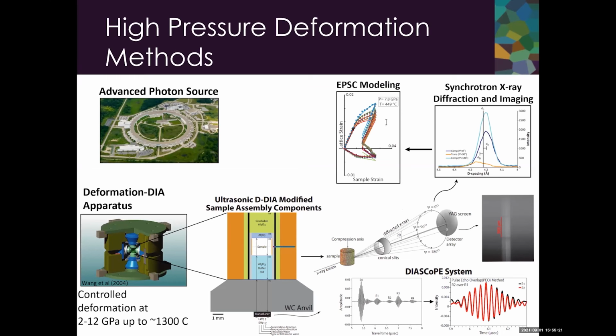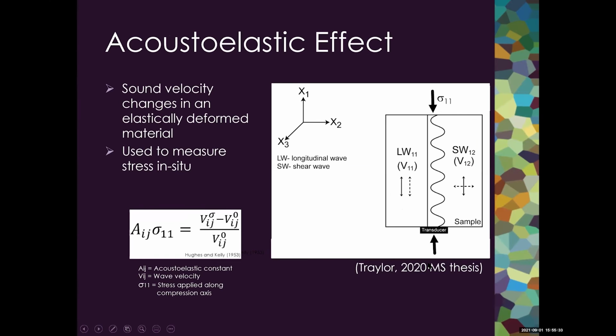So I want to transition into the experiments where we've incorporated ultrasonic interferometry, where we're now able to also obtain ultrasonic travel time measurements while we're deforming using the D-DIA system. As I mentioned, we've added ultrasonics as a probe to our experiments, and this allows us to look at how differential stress impacts the compressional and shear wave velocities of our material that are propagating along the compression direction. So this schematic to the right just shows the orientation of everything.